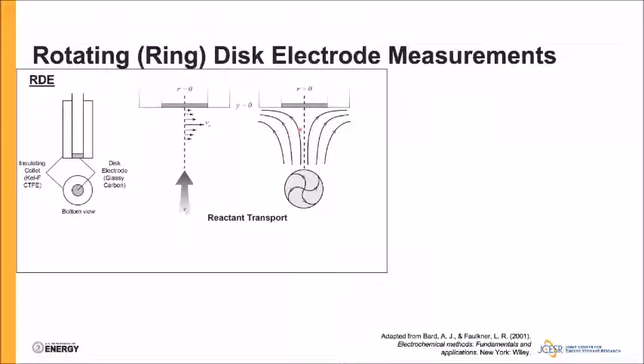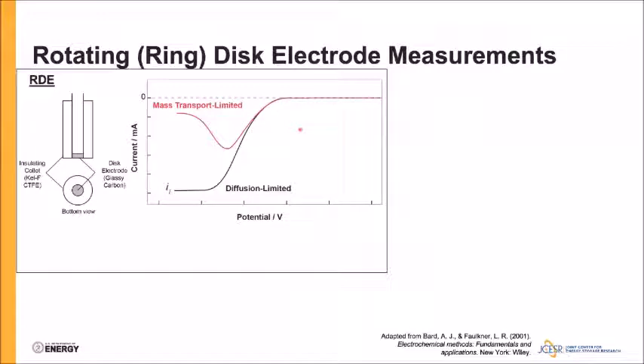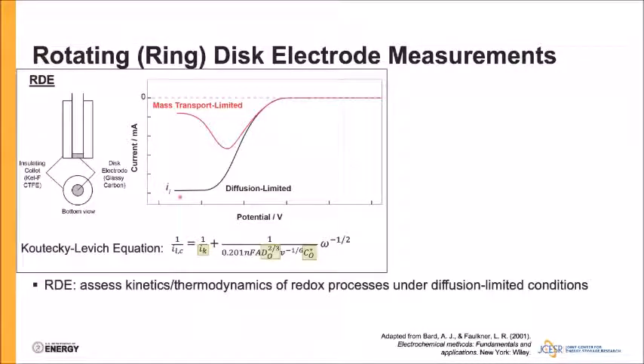The result of this is that instead of seeing peaks in this mass transport limited case, you start to see plateaus corresponding to diffusion limited delivery of your active species to the electrode surface. And what this lets you do via the Koutecký-Levich equation, if you vary the rotation rate, is extract kinetic and thermodynamic process parameters related to the process that you're studying.